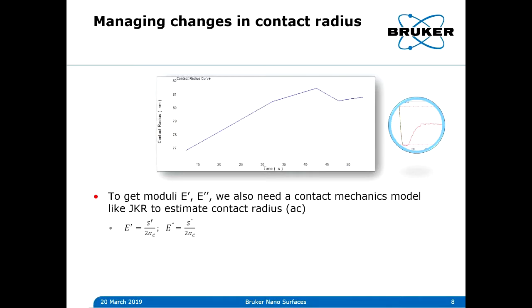To get to the moduli, like the storage and loss modulus, we also need a contact mechanics model like JKR to estimate our contact radius. This is the conversion between the real stiffness and the storage modulus. So we just divide by 2 times the contact radius, and the same is true for the loss modulus. But we need to track that, and there's an intrinsic difficulty in making these viscoelastic measurements accurately when you're doing indentation at these time scales.